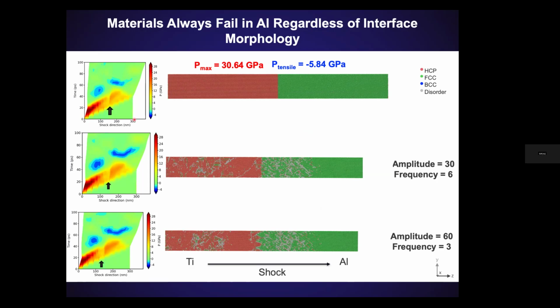If I look at the position and the time, the arrow kind of denotes where my interface is. I have three types of interfaces here. I have a flat interface, and I have two cosine interfaces with different amplitude and frequency. Remember, larger amplitude is like a bigger kind of wave. The trough to peak distance is much larger, and we also change the frequency.